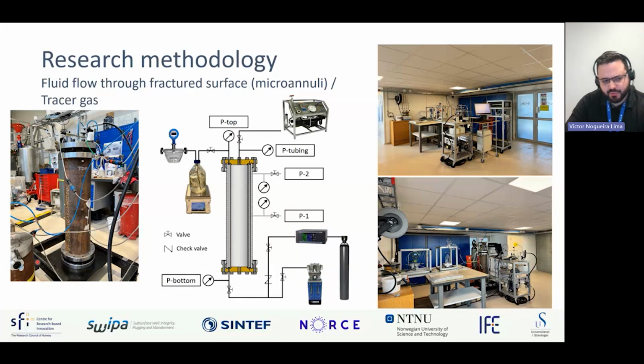For this 1 meter section, we had a 9 5/8" setup with a 7-inch inner casing. Then we cemented the annular, and we applied 150 bar inner tubing pressure while curing. After 1 week of curing, we relieved the pressure, and then we created a debonded region between the inner casing, the 7-inch casing, and the cement sheath. So in this region over here, between the inner casing and the cement sheath, we create this debonded region that is basically the fracture surface, the microannulus. So this is the object of study that I'm going to address in this part of the research.